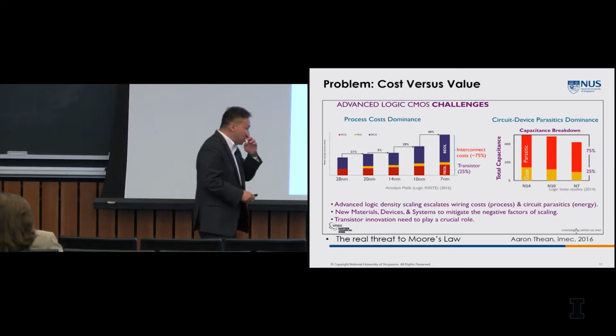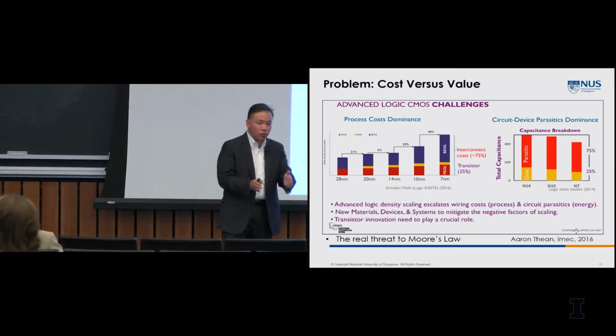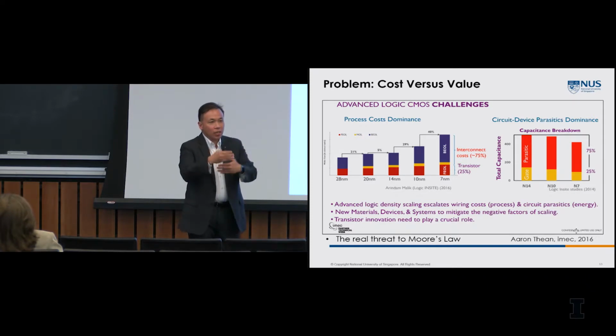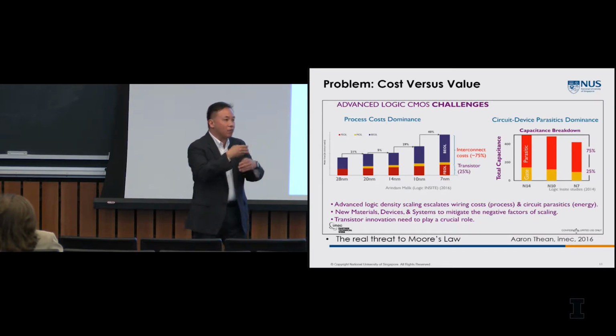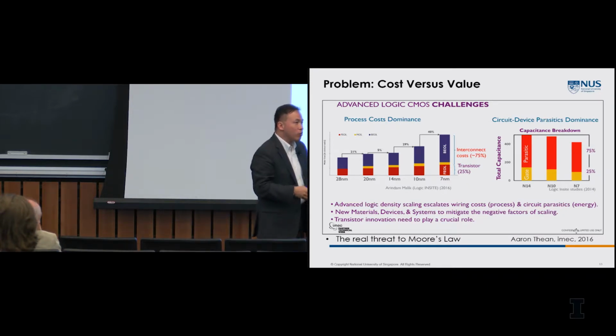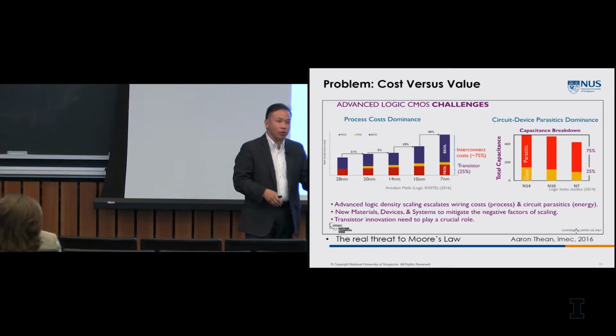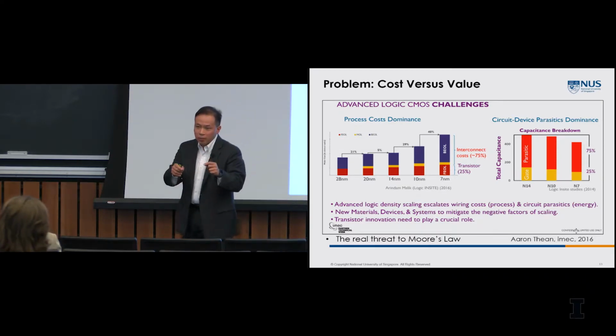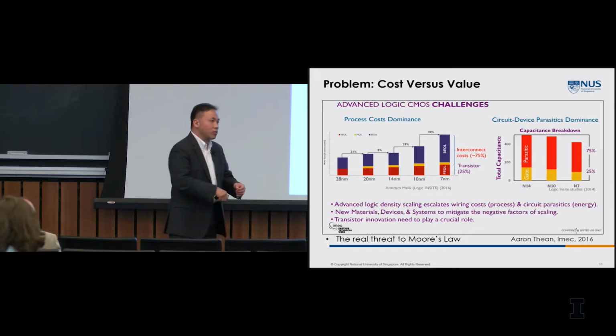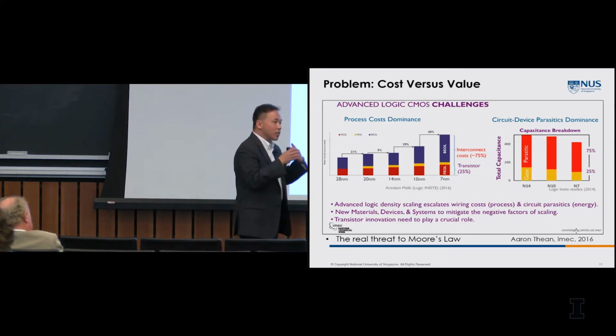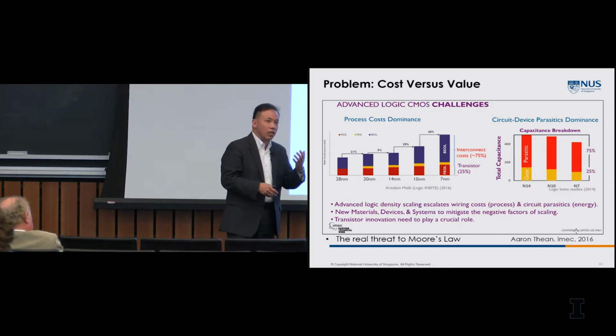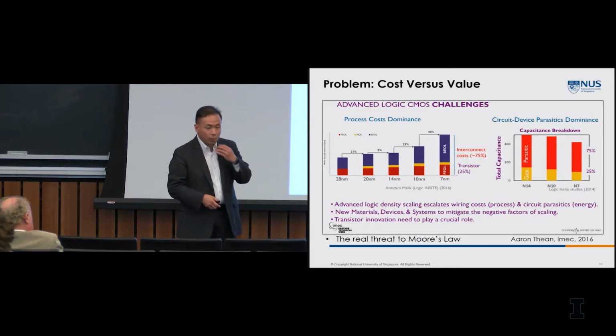And the reason for that is very simple. As I described to you previously in the fin, to get each layer of fin or each layer of structure, there were at least 4 or 5 patterning steps. In the old days, you just had to print them with your contact aligner, you print them with your lithography tool, you're done. That's your pattern. Now, in order to achieve that, you have to print, deposit, etch, print, deposit, etch. Those multiple steps basically incur cost. And that's multiple patterning cost.